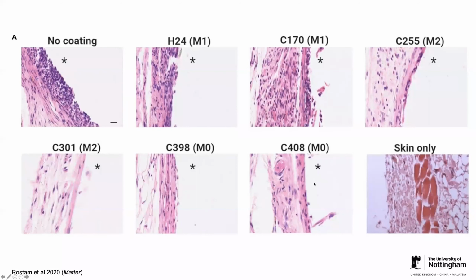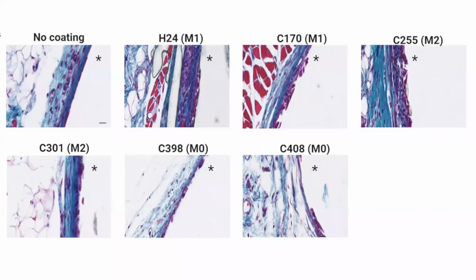So there is a modest cell infiltration, but if you look at the collagen deposition and fibrosis in the next slide, you can see that it becomes even more interesting. If you look at the uncoated, you have fair amounts of fibrosis and collagen deposition. It's a lot more for the two M1 polymers, similar levels for the M2 polymers, but what's really interesting is that in the two M0 polymers, we have substantially less collagen deposition and fibrosis.